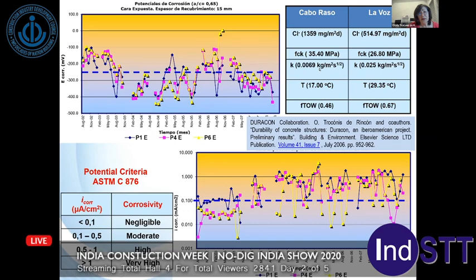the higher average temperature, 29.3 with respect to 17 degrees C in Cabo Raso, and higher wetting time. La Voz has 0.67 and Cabo Raso 0.46. Those variables increase the diffusion rate of chloride ions. La Paloma, located in Uruguay, is another non-tropical, marine environment test station, where rebar showed corrosion activity. This was installed after Cabo Raso and La Voz.